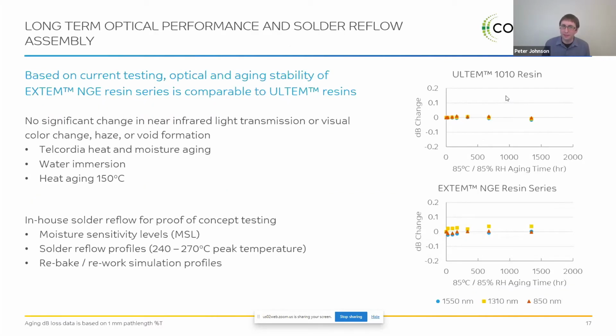And then the final thing that I just sort of wanted to cover was, again, aging processes. So when we're talking about this material, it's great if we can make it, but if it doesn't last for a long enough time, it's effectively useless. And from what we've tested so far, the EXTEM series is comparable to the Ultem resins that have been used for 20 plus years now in these optical components. We haven't seen any significant change in light transmission, visual color change, haze, or void formation.